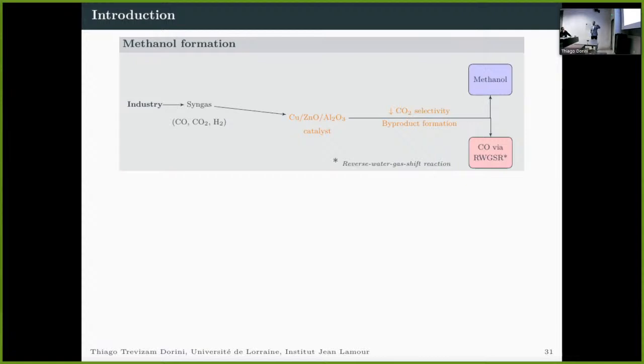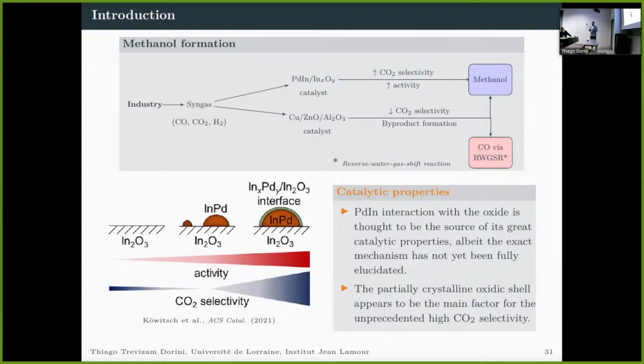In the literature, we can find an alternative material that seems to be much better than this copper-based material: the palladium indium supported on indium oxide system. This system has a much higher selectivity and activity for the production of methanol. So far, we do not know exactly why this system is so good for its catalytic properties. There are many studies trying to understand what is happening, especially this work by Kowitsch and collaborators, in which they identified that one of the main parameters that may lead to these great catalytic properties may be the interaction between a thin layer of this oxide film and this palladium indium substrate.